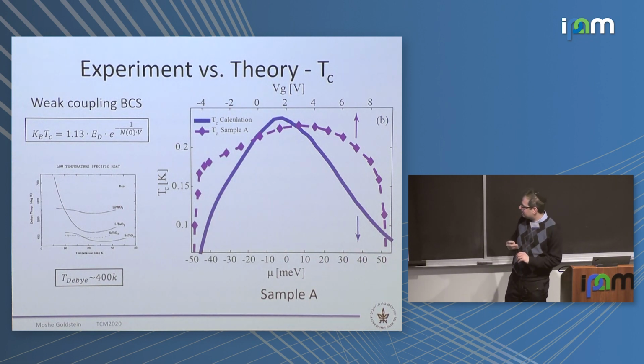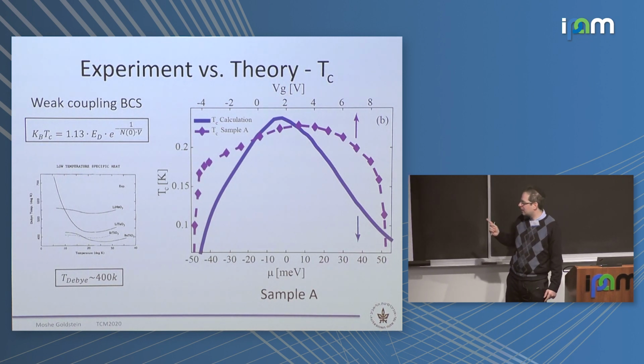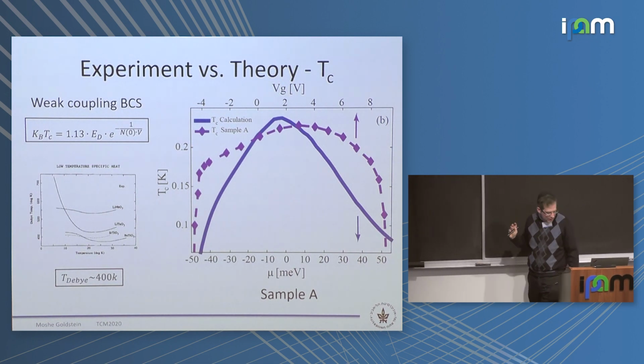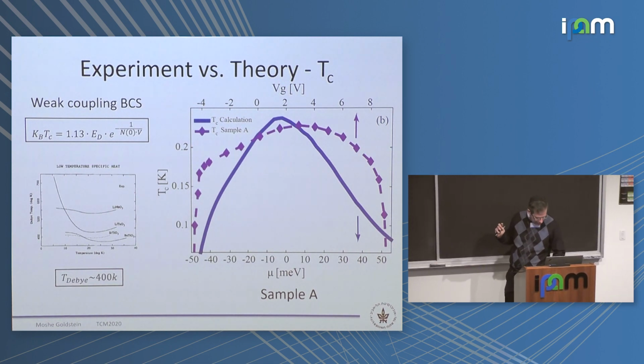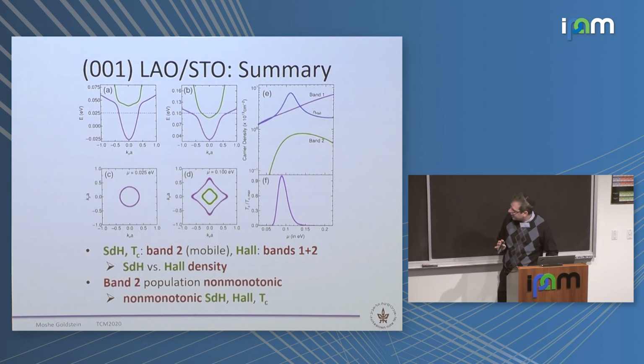And this is what I stressed before, the comparison with bulk STO. In bulk STO, you had the dome as a function of filling, and actually here you have a dome as a function of chemical potential or Fermi energy, and this is not the same because the density, at least of one of the bands, is non-monotonic as a function of that. So there is a different mechanism in play here. And okay, this is a summary of all those things I was telling you.